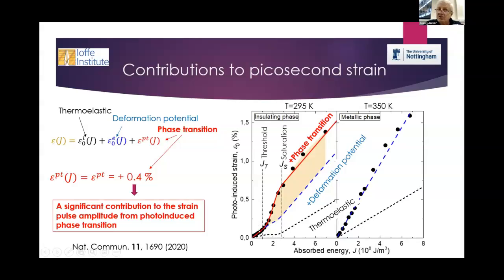So there is an energy when phase transition starts, and then the strain pulse amplitude goes rapidly. It increases rapidly, and then when we go to the power which corresponds to the saturation, so all material in the film, excited material is transformed to another phase. Then again, we have some linear dependence.